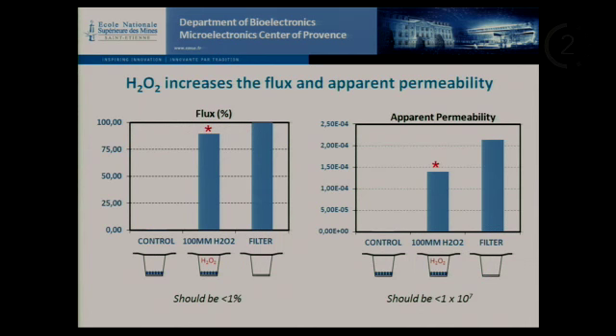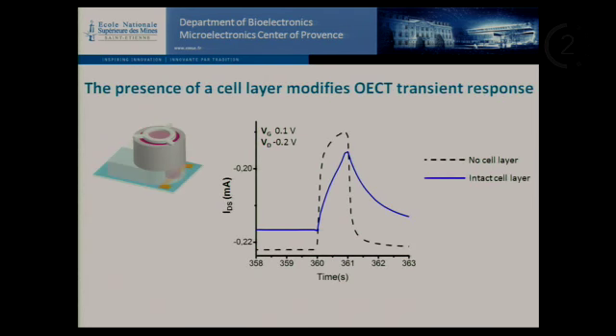We have also shown in our lab with permeability assays that compared to a healthy control, the addition of hydrogen peroxide greatly increases flux and apparent permeability. So we can also show this same effect with our OECT.